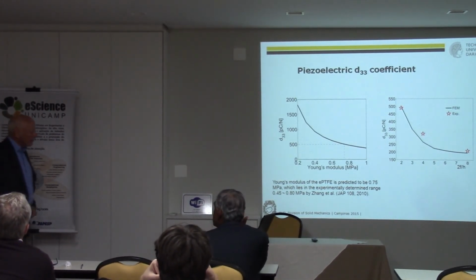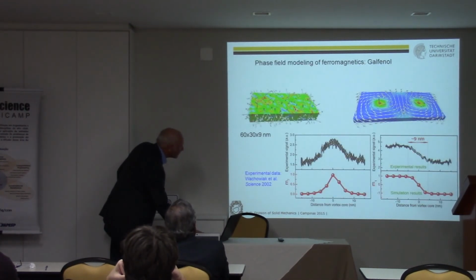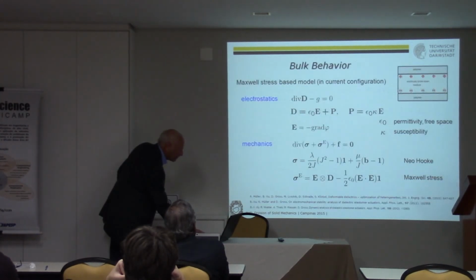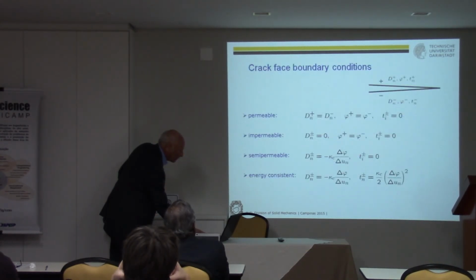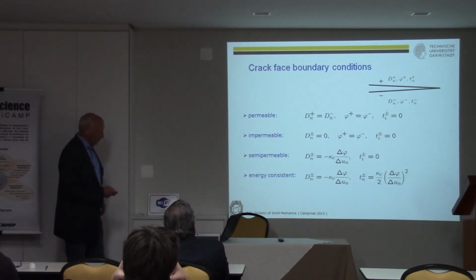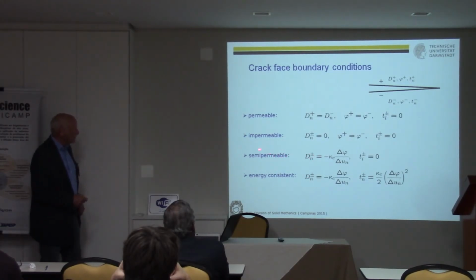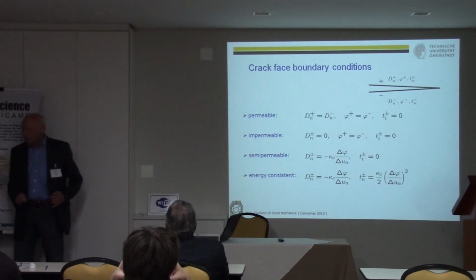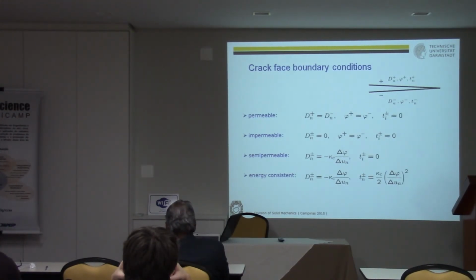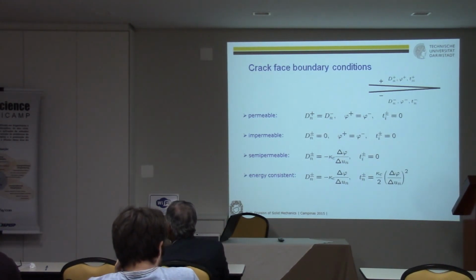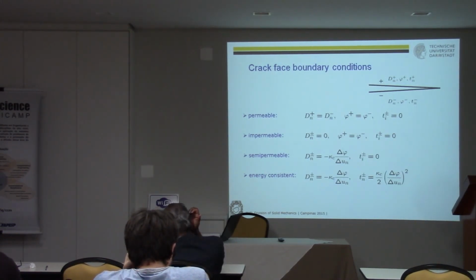This is relatively easy. Here you see for the semi-permeable system and for the energy consistent system, you need a constant here, yeah, the susceptibility of the material, yeah, and the susceptibility in the gap between the upper and the lower crack face, yeah, this is air, yeah, dry air or humid air. So yeah, it goes into the electric properties of the material, yes, not the mechanical. Just like changing the dielectric constant of the void. Yeah, of course.